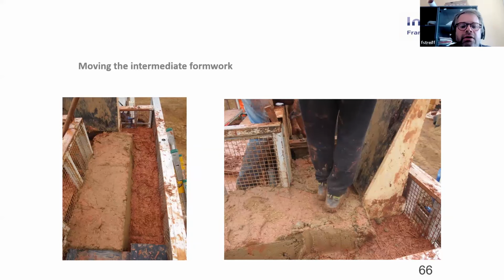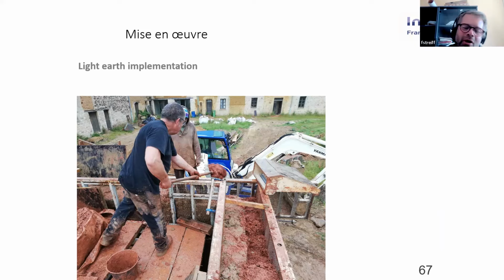And just by moving this intermediate formwork, we had a gap here that we could fill with light earth. So we proceed a bit like rammed earth finally, with small layers. For rammed earth, a layer is about 8 centimeters high. Here we could build 20 centimeters high, but we use very small layers, a small layer process. The light earth, same thing.